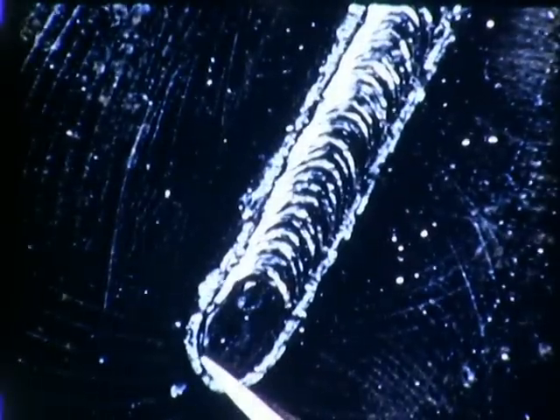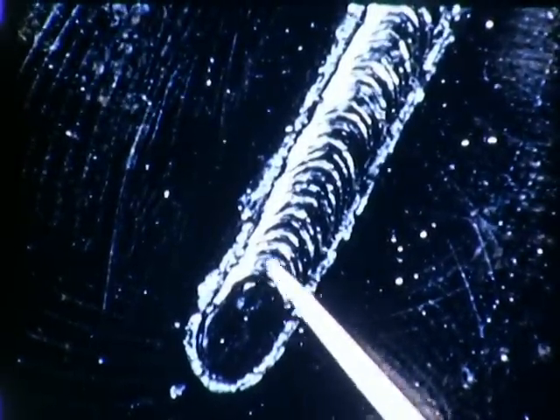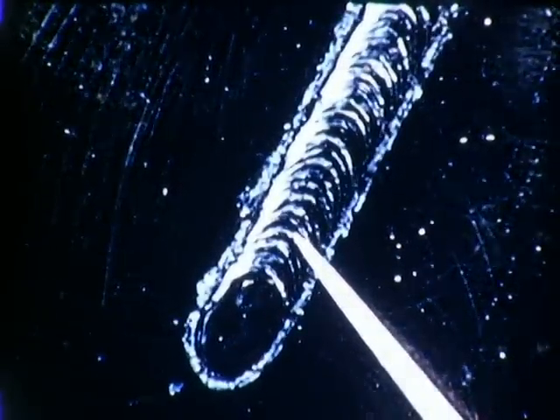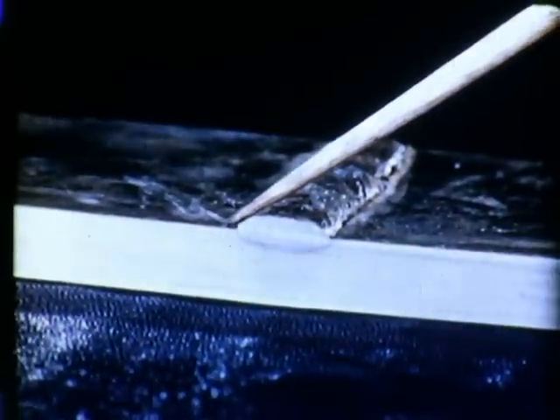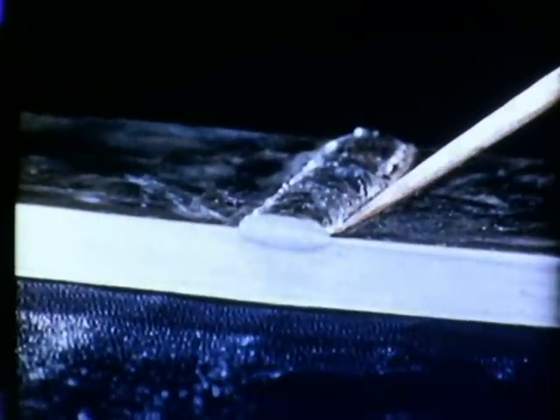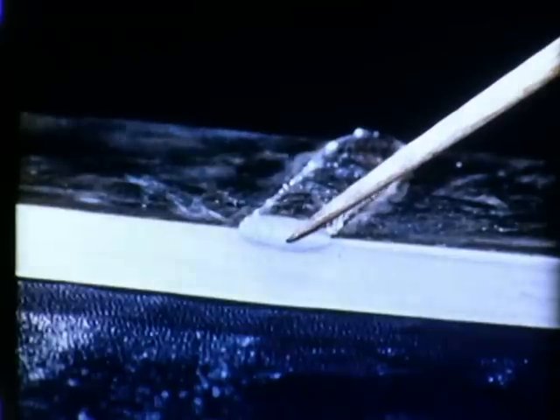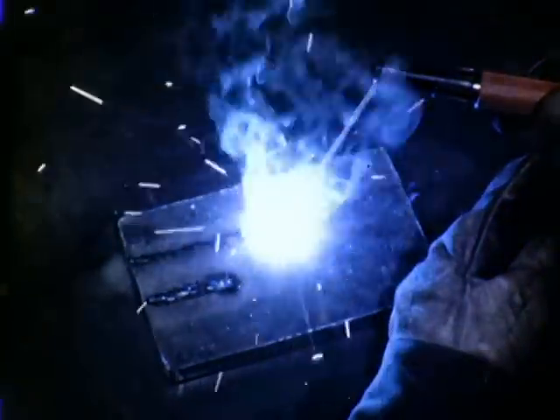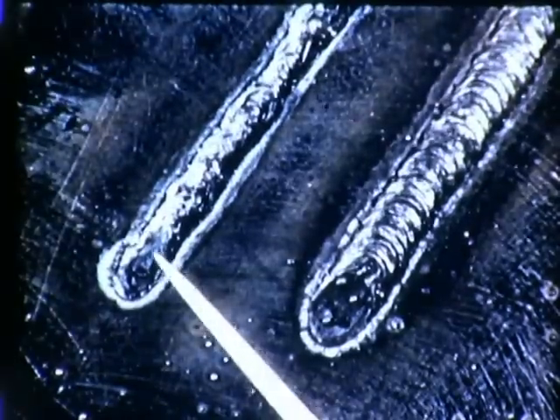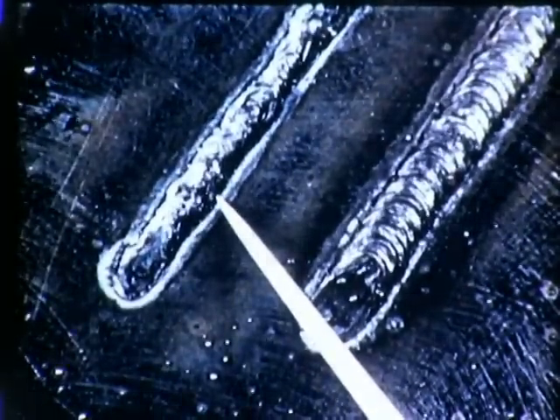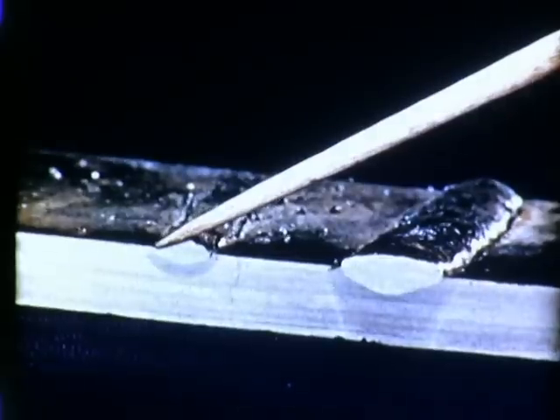When the speed of travel is correct, the bead forms in an oval shape with an oval crater. The ripples are uniform. The bead will have good shape with the right fusion and penetration. If travel is too fast, the metal forms gas pockets. The ripples will be pointed and the bead very narrow. Penetration is irregular with undercut on each side.